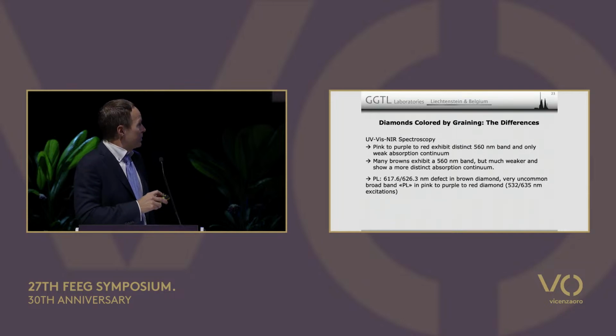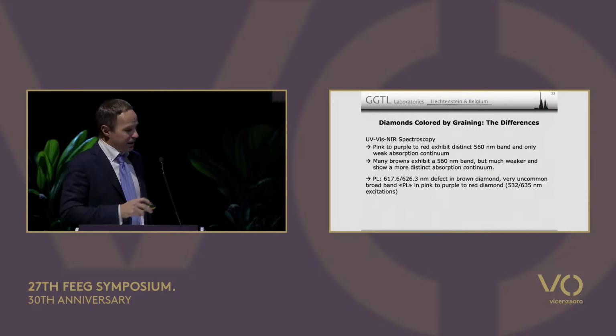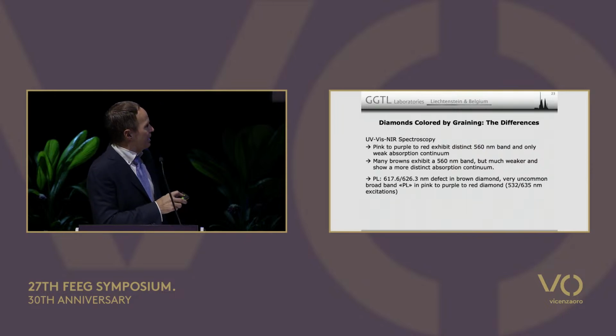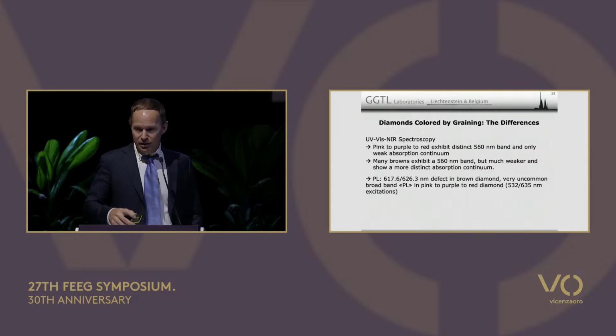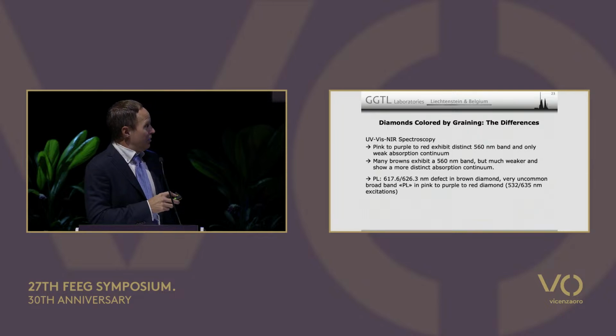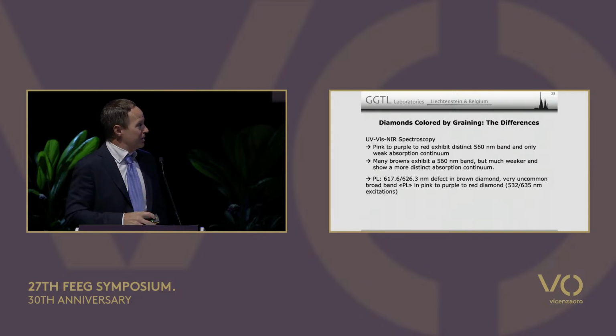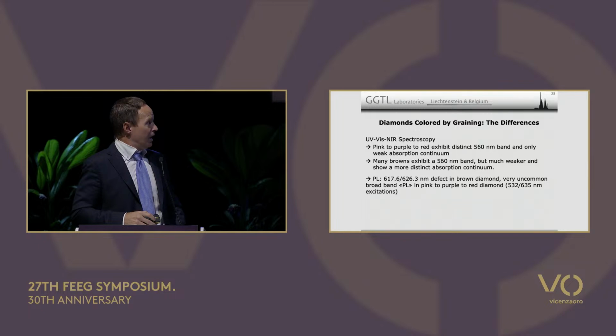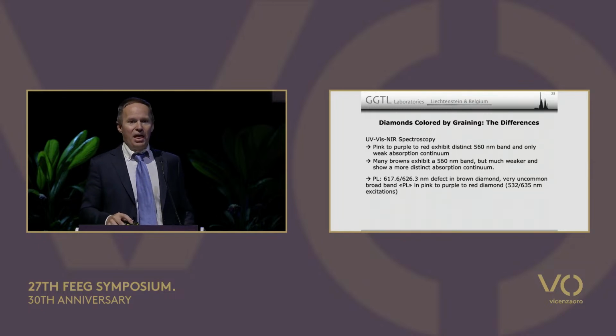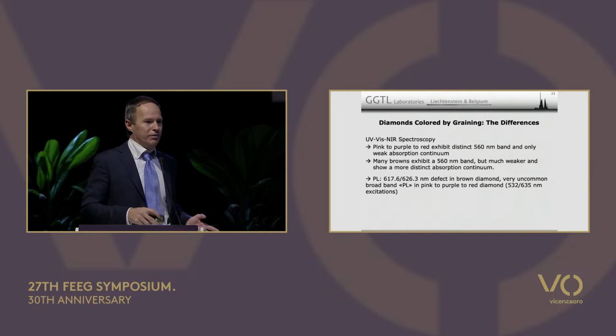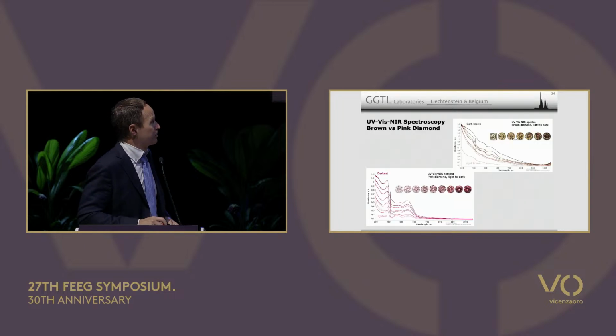And then one important thing in the photoluminescence spectroscopy is this band here, this funny and strange band that is almost omnipresent in brown diamond, and it's very, very uncommon in purple to red diamonds, and usually only present if you have brown lamellae in the stone.